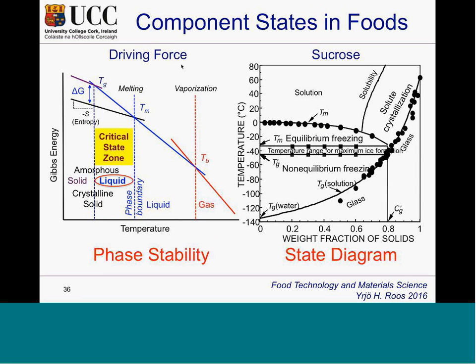This diagram is quite fundamental to understand. The one was published with Professor Karel, but I would like you to pay some attention to this driving force system, which is showing typical transitions in materials. Temperature, glass or liquid, we see melting, we see glass transition. You don't need to care too much about what the material is, but think, for example, that this is sucrose. You would have sucrose melting at around 190 Celsius. Rapidly cool the sucrose, make a candy, and you cool it to 50 degrees without water to get it into the solid state. Now you do that, you only cool the material, but you can probably cool without crystallization. So it forms a glass, vitrifies.